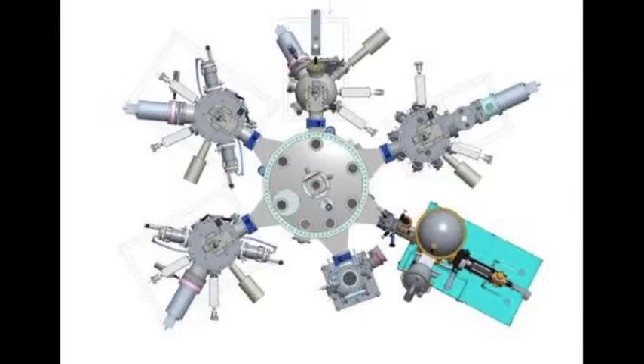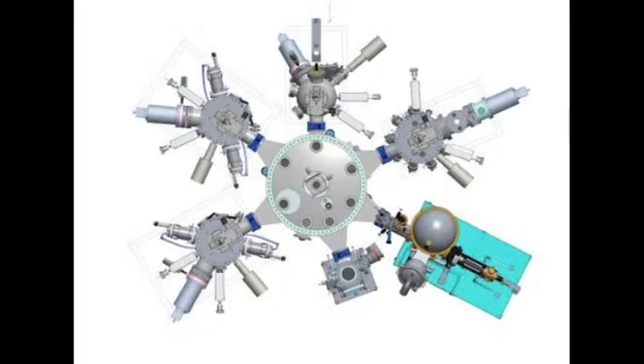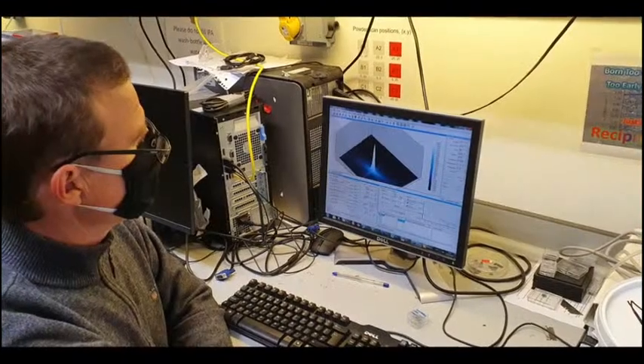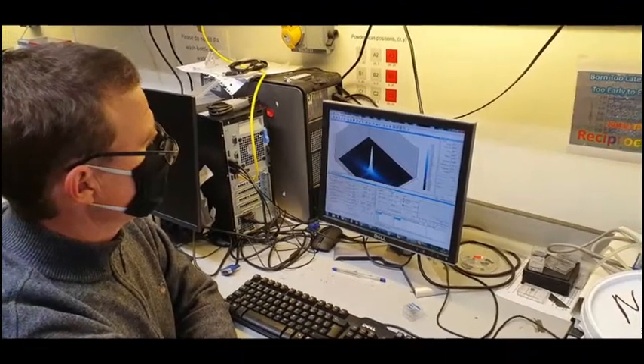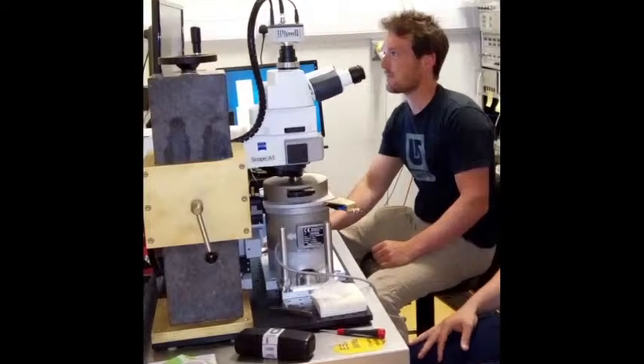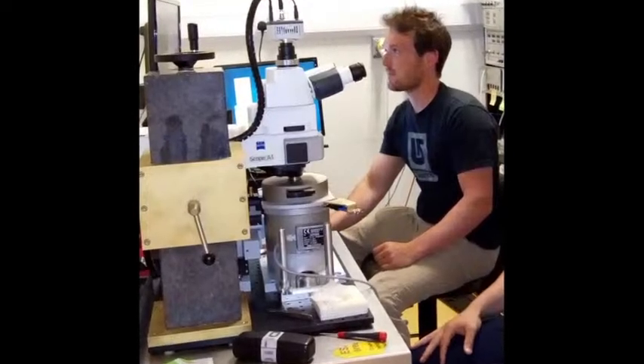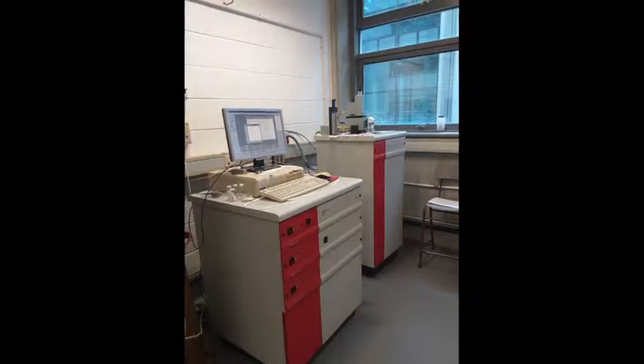And we're really lucky to have the new €3 million TEDI facility where we can make near-perfect devices by sputtering in ultra-high vacuum. The tool also includes chambers for in-situ study of the films just after we produce them. They must be thoroughly characterized by X-ray diffraction, microscopy to see if there are any magnetic domains, and then by SQUID magnetometry over in SNIAMs.